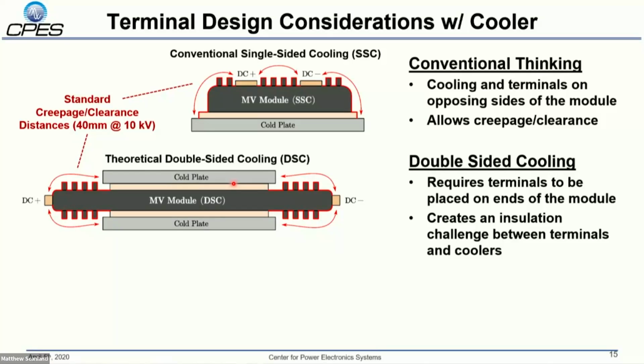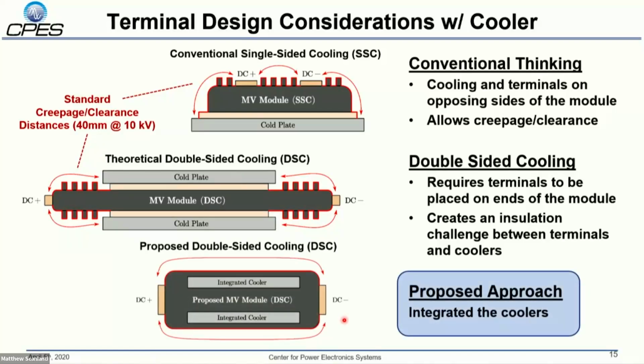So part of our strategy is to actually integrate these coolers directly into the module. And when we do that, we end up with a shape that looks a little bit like that. So now these coolers have been moved inside the module, and we don't have to worry about that creepage and clearance to the cooler itself. We're now only concerned about what happens between the terminals. So this allows us to decrease that lower bound on the power density.